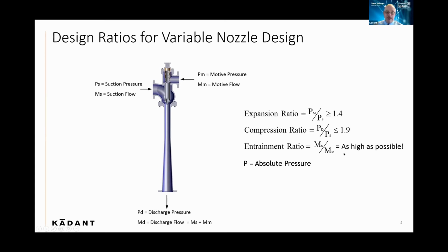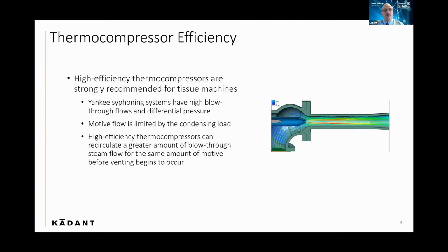And the entrainment ratio is really the amount of suction flow over the motive flow. And we like the entrainment ratio to be as high as possible, especially on Yankees. That's the reason why we recommend what we call high efficiency thermal compressors, because on a Yankee, your motive flow is limited by the amount of your condensing load. So that's why it's important to do that rate of rise test. If the motive flow exceeds the condensing load, then we will never be able to close loop the blow-through, and it's going to result in some venting.